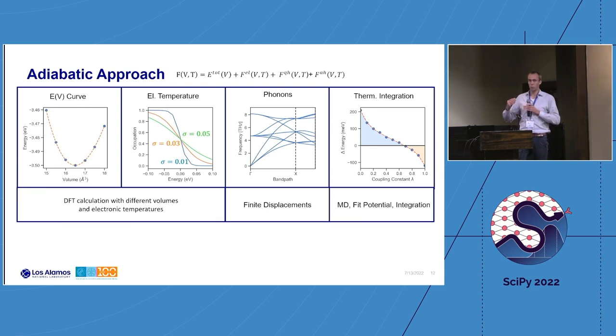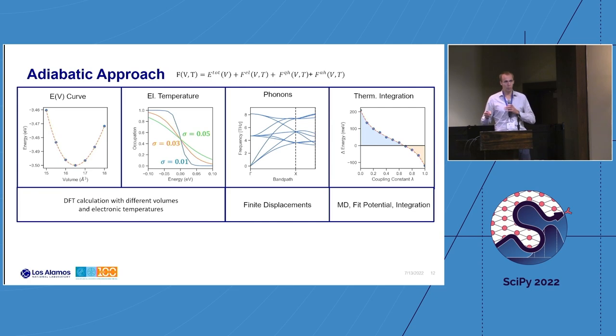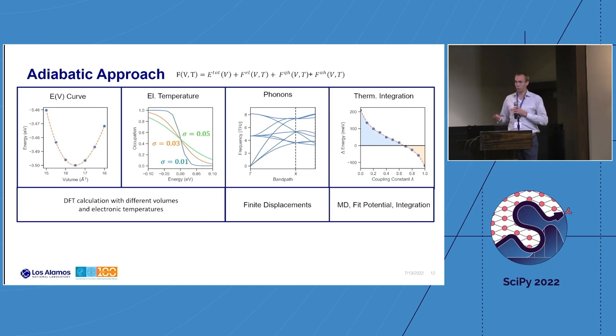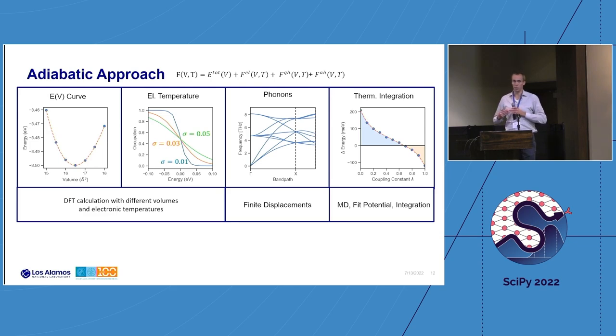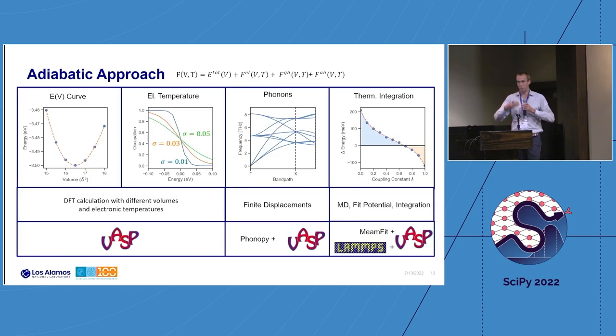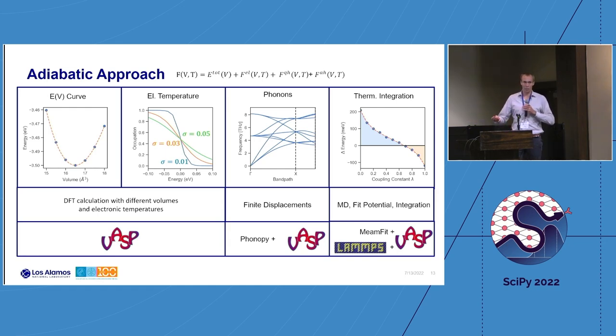Finally, we use thermodynamic integration to go from the harmonic model to the full anharmonic free energy. This requires different kinds of codes: for the energy-volume curve, a simple DFT code; for phonons, a specialized code considering different levels of symmetry; and for thermodynamic integration, we run a short DFT-MD, fit it to atomic potentials — such as machine learning potentials — then do the integration by coupling the ML potential directly to DFT. In practice, I use VASP for the first two levels, then couple VASP with Phonopy, and finally VASP with LAMMPS and a potential fitting code.